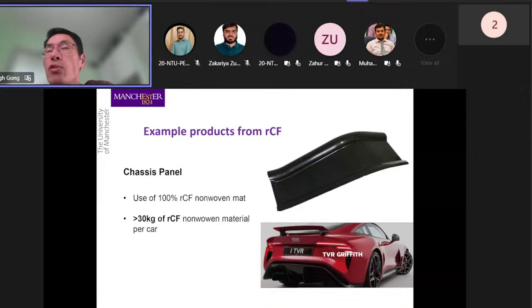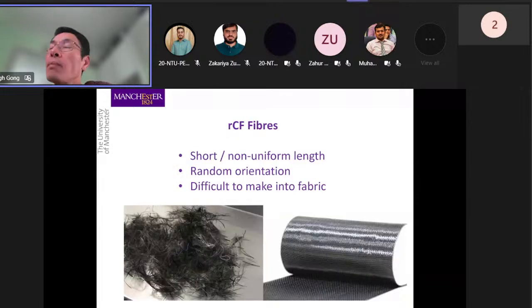Now, the main issue with recycled carbon fibers is that they tend to come in a very short form, a bit like staple yarn production, so they are staple fibers in the end, short. The other thing is that the length tends to vary dramatically. Some very long, some really very short. The other one, of course, because of the way the fibers are reclaimed, they tend to be very randomly orientated. And that's going to cause problems in terms of application, especially if you want to make them into unidirectional composites or fabrics where you can control the fiber alignment, which actually is one of the most important aspects of what we have been trying to do.